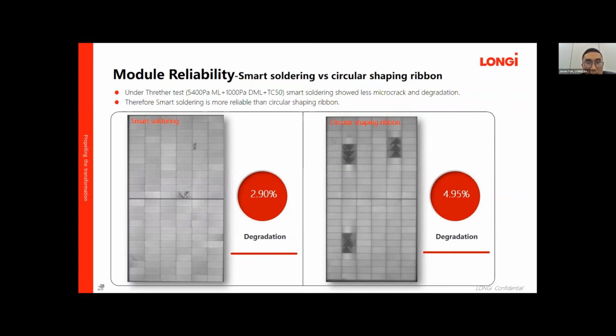We can find that the smart soldering showed less micro crack and degradation. The micro crack is only 2. However, for the circular shaping ribbon, the number is too big, and the degradation is almost close to 5%. So therefore, the smart soldering is more reliable than the circular shaping ribbon.